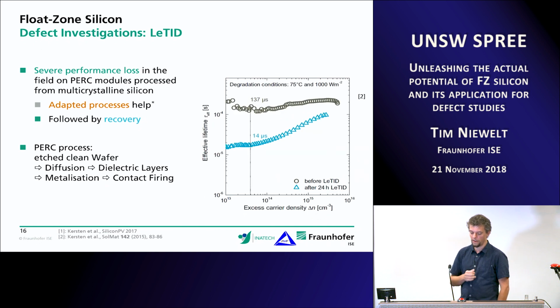It has already been shown in the past that the degradation also occurs on wafers, so not just on solar cells or solar modules. Here, for example, is a result on the effective lifetime of a wafer before and after degradation. In this case, it's even wafers without a diffusion, so the diffusion can be ruled out. That's not causing the problem. Then the metallization is also not the problem because these wafers didn't see any metallization treatment, so we can rule that out as well. Leaving three more things that we can have a look at, so the dielectric layers that